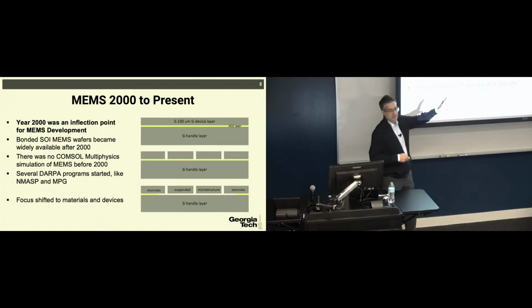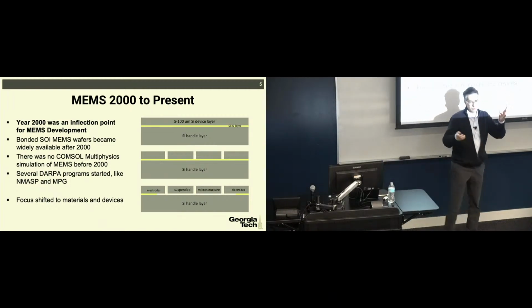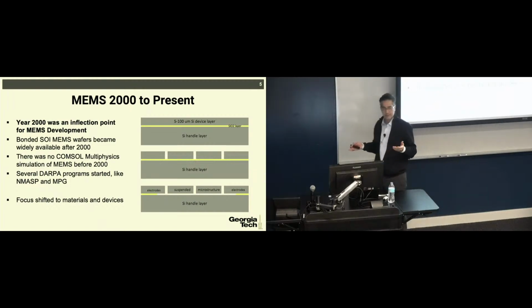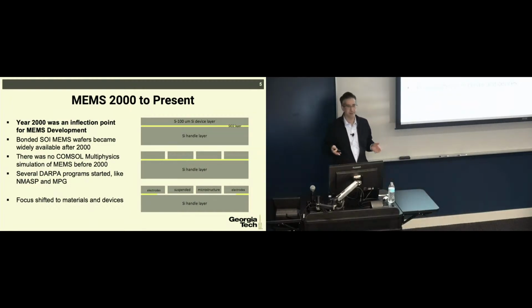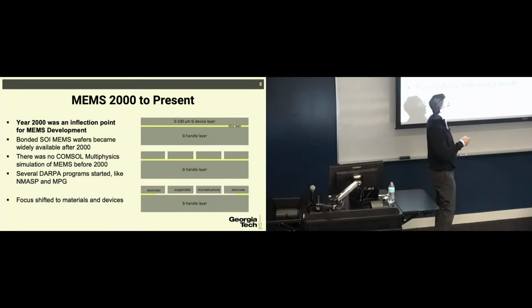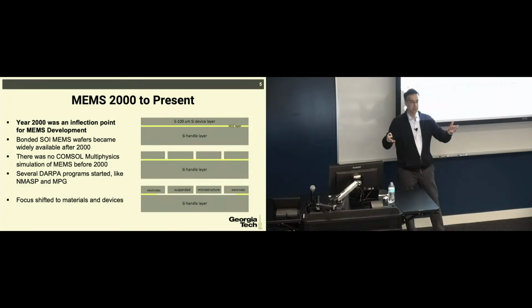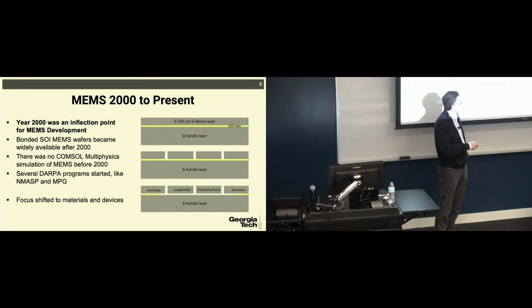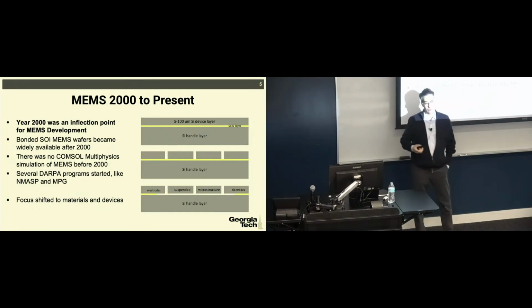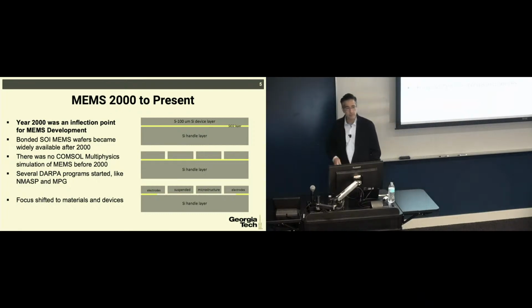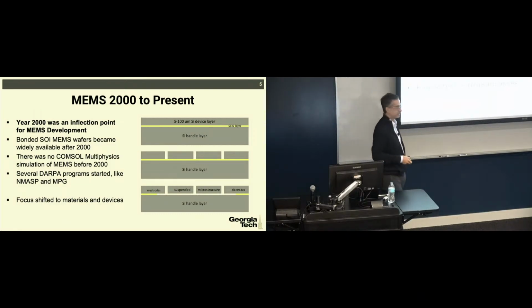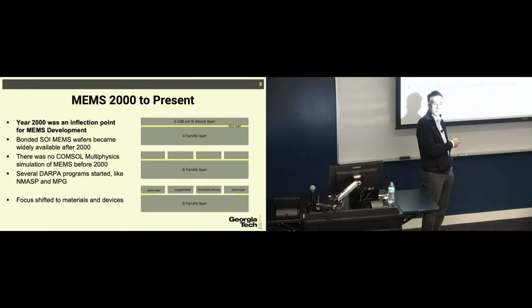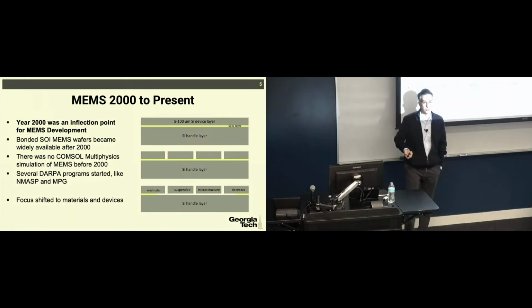And the beauty of it is that once you get it, then most of you guys probably know about the Bosch process, the silicon deep RIE process that enabled etching trenches into the silicon substrate. You can use that process, literally one mask, to etch these straight trenches into the silicon device layer to create a structure. Then you release that oxide layer through a hydrofluoric acid etching, as acting as a sacrificial layer, and voila, you have now a MEMS device that is ready to use.